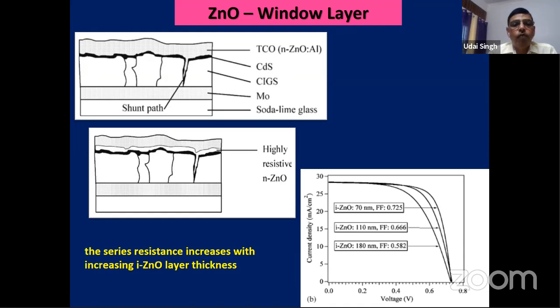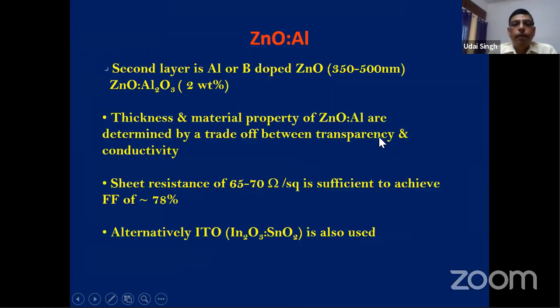So what they have tried to do is coat this with a highly resistive N-type zinc oxide. So it will avoid the shunting path. You can see that if your intrinsic zinc oxide thickness is 70 nanometer, you get a good fill factor. But if you increase this thickness, your fill factor will reduce. And then the transparent conducting oxide is mostly zinc oxide, aluminum doped zinc oxide.